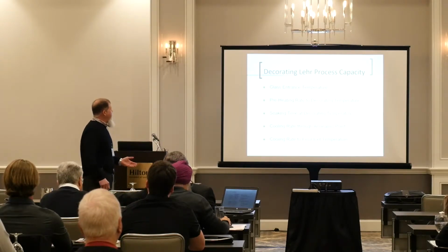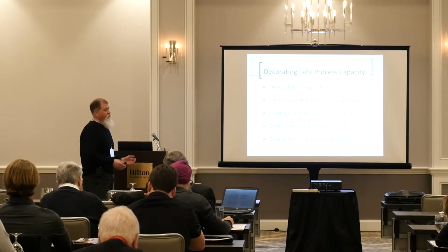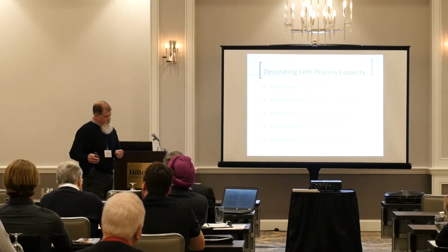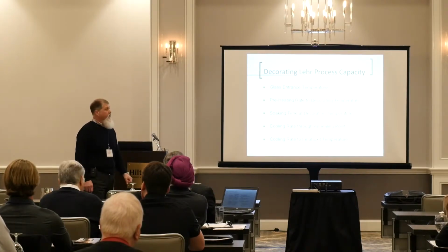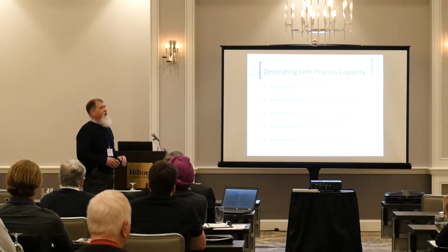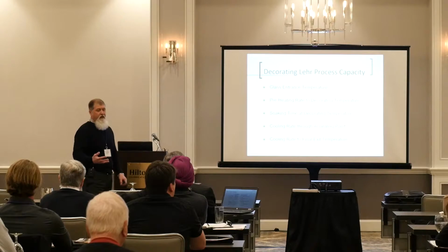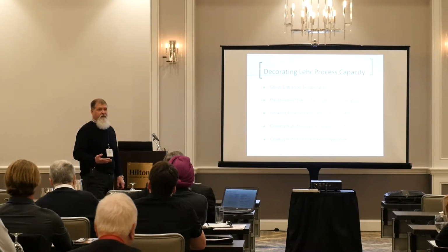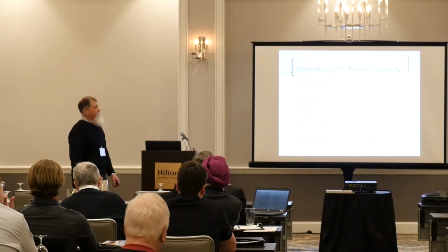So regardless of what the quality of the annealing was when you receive it, once it's gone through your decorating lehr, you're now responsible for that. So I don't know if everybody here has the ability or has that as part of their process to grade annealing after you've fired your ware, but it is something that you need to be aware of, especially if you're doing pressure items, anything for the beer industry or anything that's going to be a pressure item specifically. You want to make sure you know where you are with your annealing grades. And then again, finally, cooling rate to your final exit temperature.